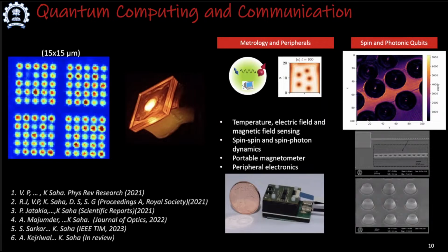In fact, it is very difficult to extract single photons out of the diamond, and it is one of the challenges. Therefore, people make photonic structures, for instance solid immersion lenses, as you can see here. This is basically a little dome-like structure built around a single photon source, so the source is in the center, and you can build a photonic structure that enables you to outcouple the light very efficiently.